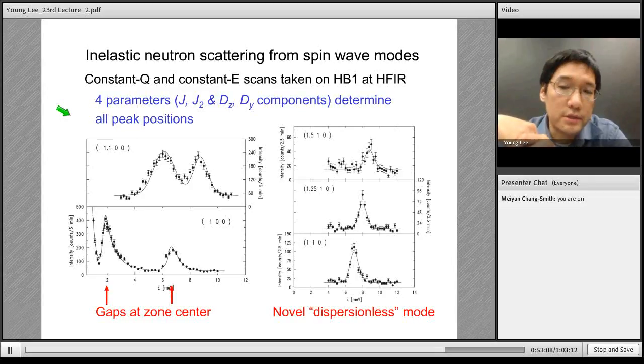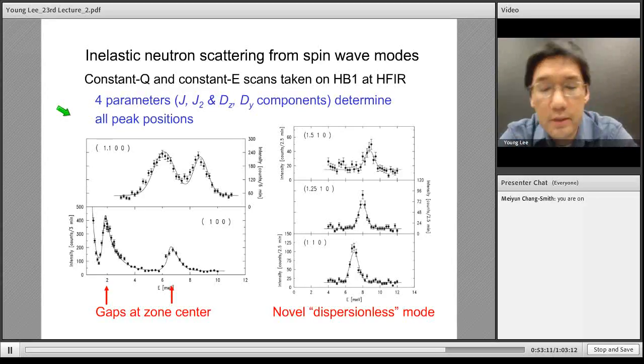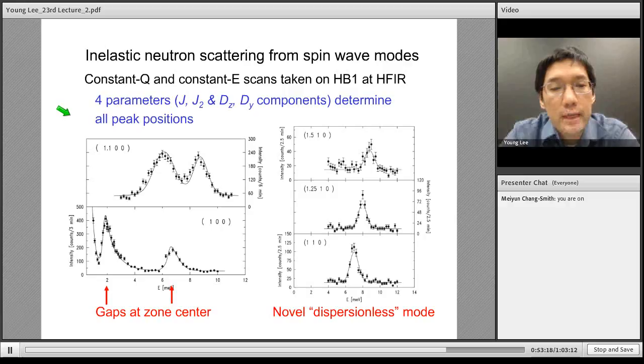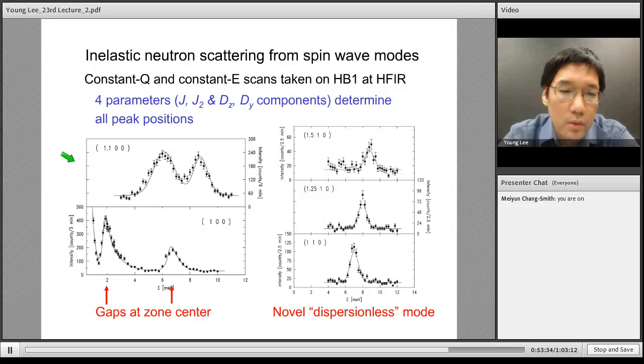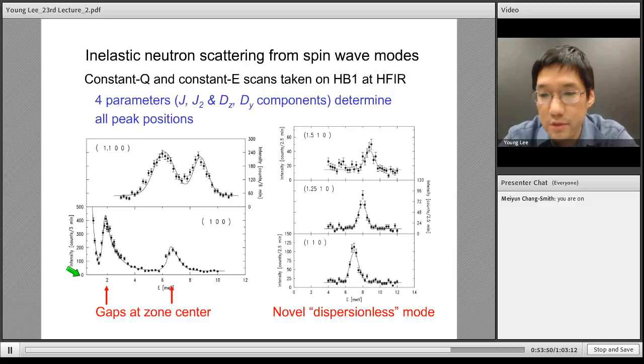So here's some inelastic neutron scattering from the single crystal of iron jarosite. We did this at Oak Ridge on HB1, and we did various constant Q and constant energy scans. Essentially for all of the different peaks that we measured, you just need 4 parameters: your Heisenberg exchange, your further neighbor exchange, and then your components of the Dzyaloshinskii-Moriya vector to determine all the peak positions. So we're looking here in this first panel at the spin wave peaks. This is at the zone center on the bottom, and here is slightly away from the zone center. You can see them disperse to higher energy. So we do have 2 gaps at the zone center.